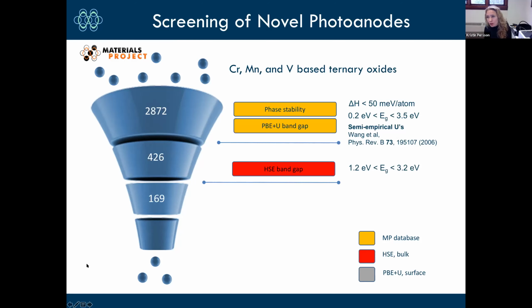Now we're down to 400. In those days, that was acceptable for doing HSE calculations. HSE is another functional that tends to do a bit better on the band gap. So now we can tighten the criteria for the band gap to 1.2 to 3.2, and we're now down to 169 possible candidates.